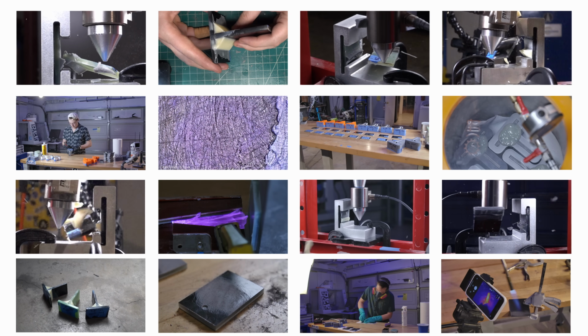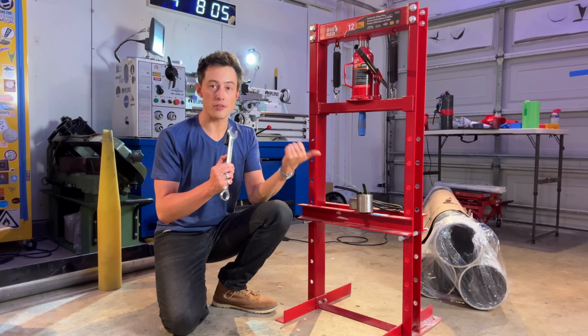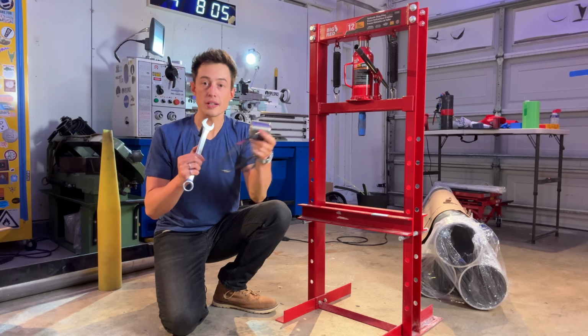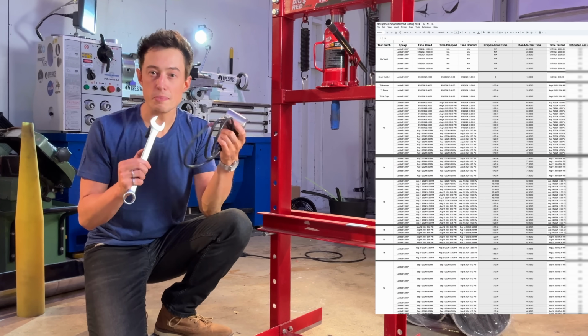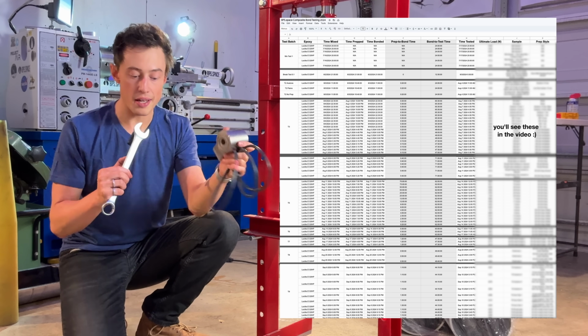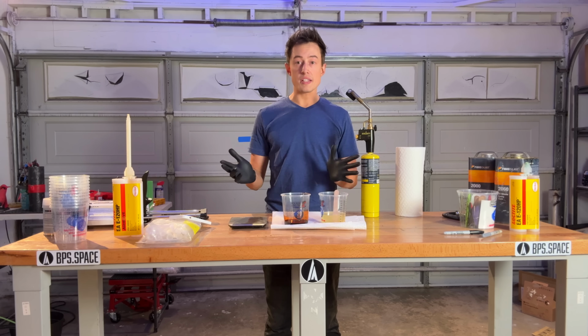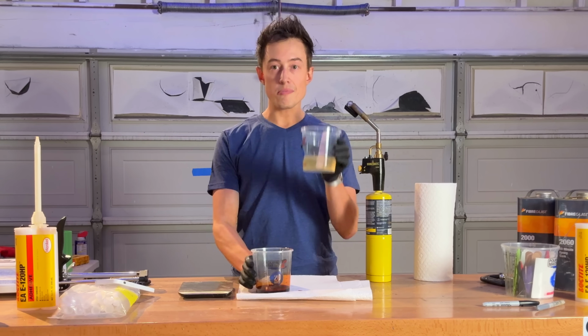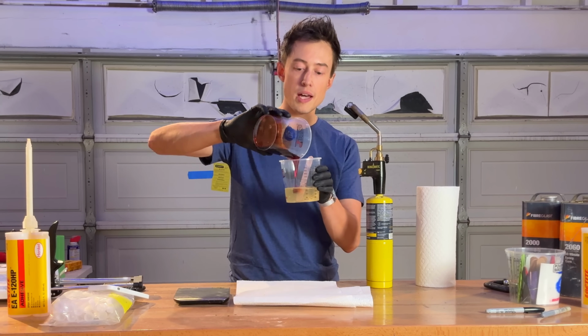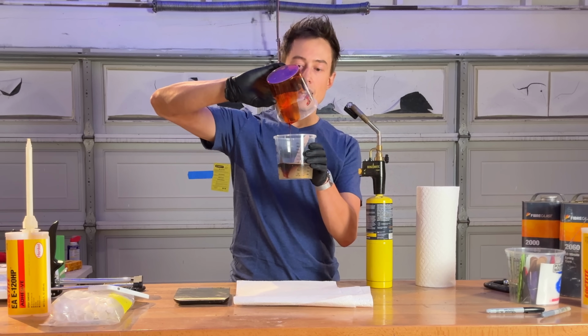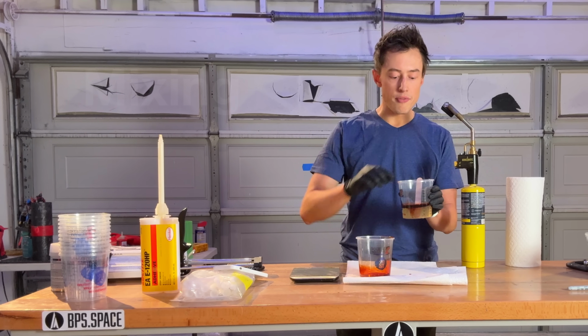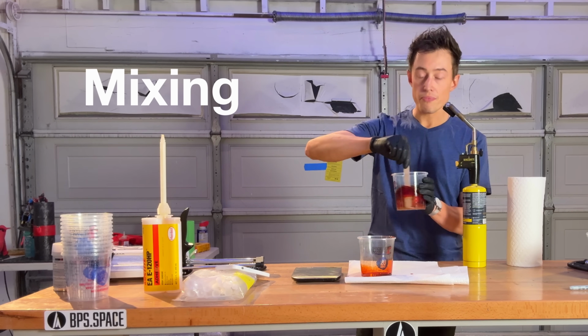For this video, I ran almost 100 tests, pushing composite coupons until they broke using this hydraulic press. I measured that result using a load cell to make sure I knew as much as possible about bonding composites together using epoxy. This stuff comes in 2 parts, a resin and a hardener, and when you mix the two together, the epoxy begins to cure. And already before we've begun, we have a variable we need to control for: mixing.